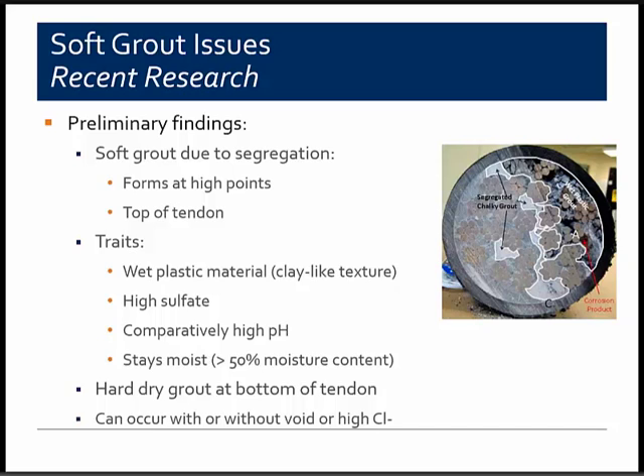And soft grout can form irrespective of the chloride content of the grout. In other words, this issue is different. It's not tied into or related to the chloride issues that we've previously discussed. It's a different issue. And in addition, although the segregation leads to these regions of soft grout, there is not necessarily a void that forms, nor does there need to be a void to have corrosion problems.